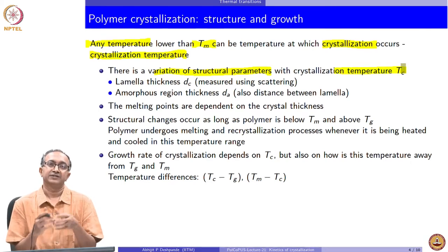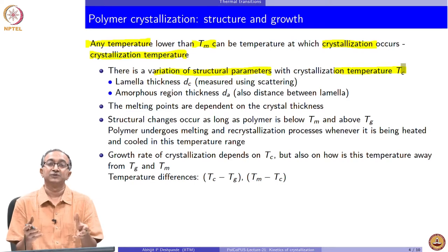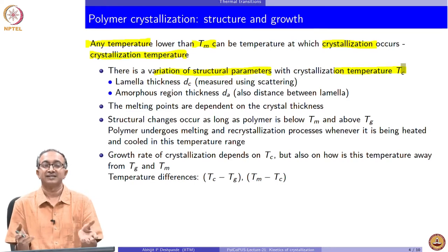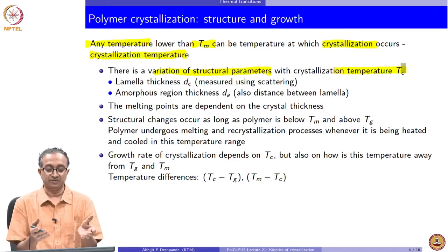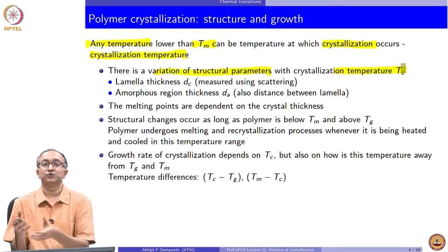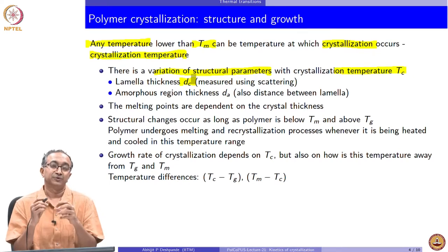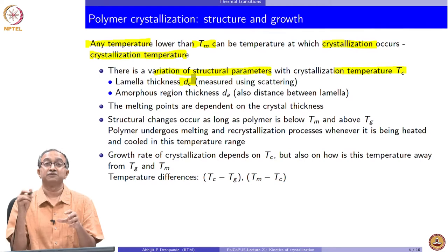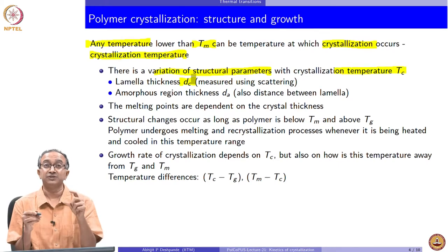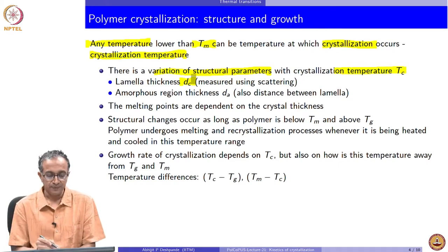If PET is taken to 280 degrees Celsius for molding and then brought suddenly to 170 degrees Celsius, it will crystallize at 170 degrees Celsius. The crystal size obtained will be different if we bring it down to 200 degrees Celsius and crystallize there — measurable using the thickness of the lamella. The thermal energy and segmental flexibility determine the rate at which polymers fold, and therefore the thickness of the fold also depends on the temperature.